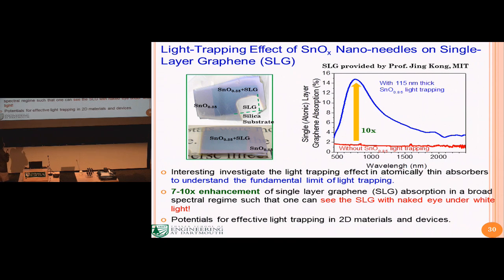And this is another sample we prepared, basically repeating the results. Scientifically, this is because we have greatly enhanced the absorption of graphene by this kind of light trapping structure. So it increased by 10 times in the red and infrared regime. It's because more of the red light is being absorbed, so most of the color you see from the white light is bluish. That's why we have this blue shade over here.